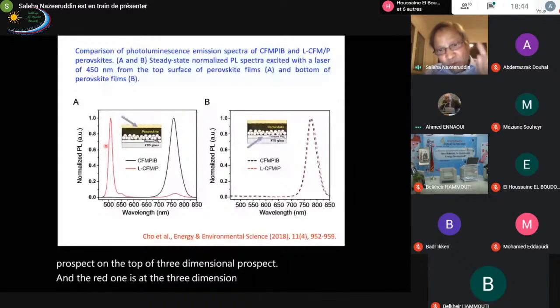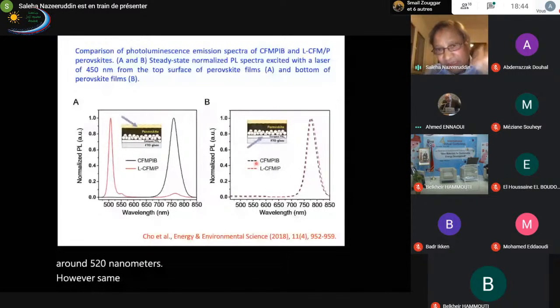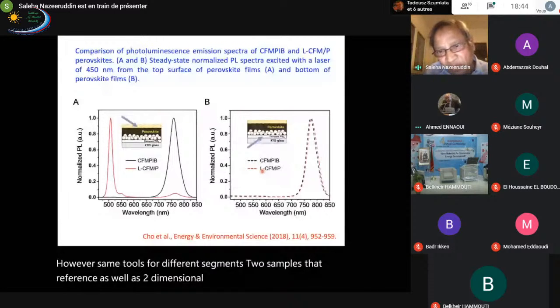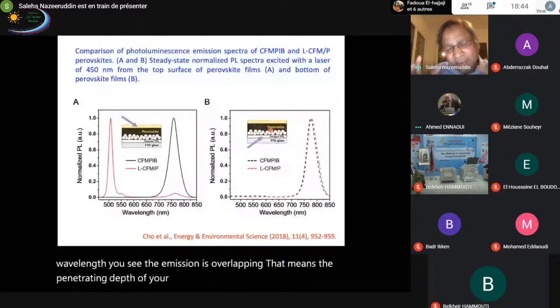However, for the same two samples, the reference as well as the two-dimensional perovskite deposited on top of the perovskite, if you excite from the bottom at the same wavelength, you see the emission is overlapping. That means the penetration depth of your excitation laser is hampered by the three-dimensional perovskite. It clearly demonstrates the presence of two-dimensional perovskite on top of the three-dimensional perovskite. Now I move to the next slide, where you see the efficiency. Not yet.